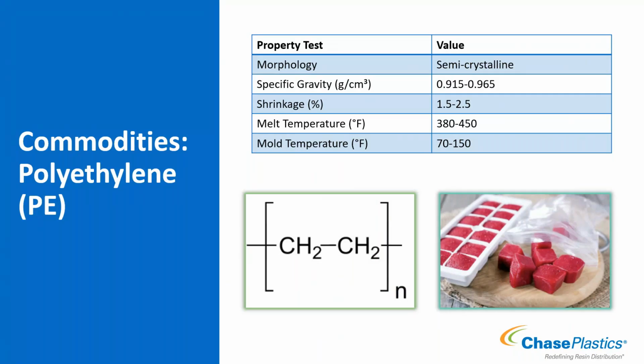Polyethylene morphology is also semicrystalline, just like your polypropylene is. A specific gravity range of 0.915 to 0.965. You'll see when we talk about the different densities, high density, low, linear low, on the next slide, that's the reason for your large range in specific gravities. Being semicrystalline, it does also shrink quite a bit, so you're in the 1.5 to 2.5 range. Your temperatures are still in that 400-ish range, and your mold temperatures in the 70s to 150s.